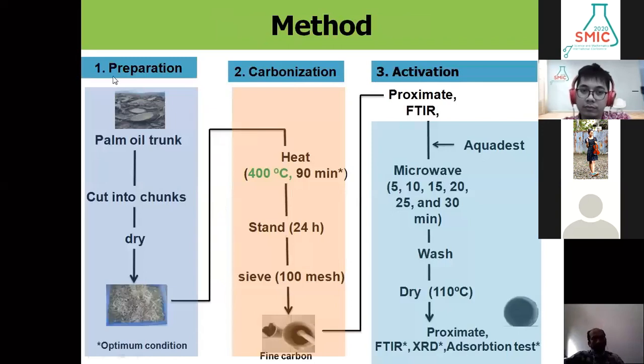This is the method. There are three steps in the preparation of activated carbon: preparation, carbonization, and activation. From the palm oil trunk, we will cut it into small chunks and then dry it. Then this is the sample which is ready to be carbonized. We will heat at 400 degrees Celsius for 90 minutes of carbonization. This is the optimum value after some experiments. This will be left to cool by standing for 24 hours. Then we will sieve with 100 mesh, and we will get fine carbon. Still, it is only carbon, not activated carbon yet.